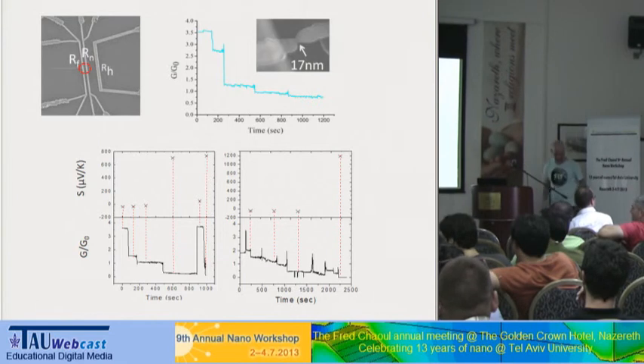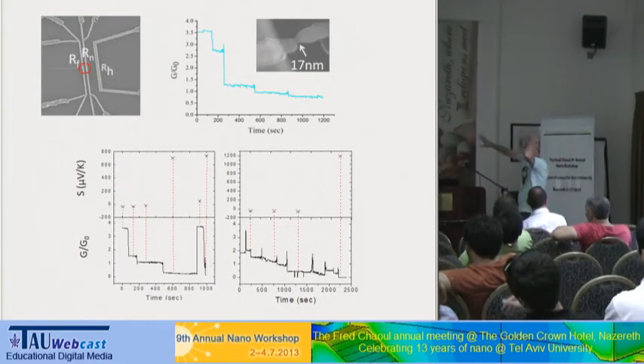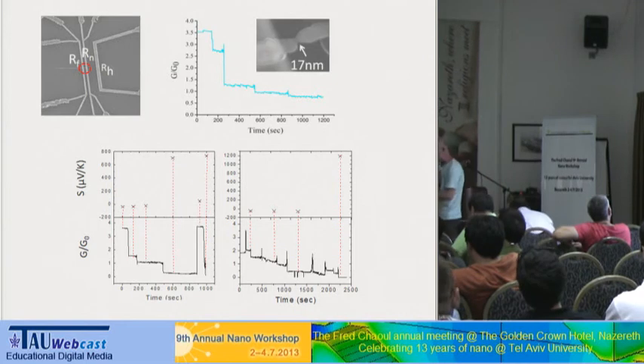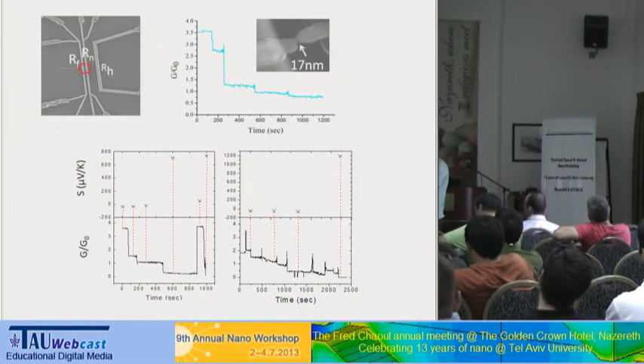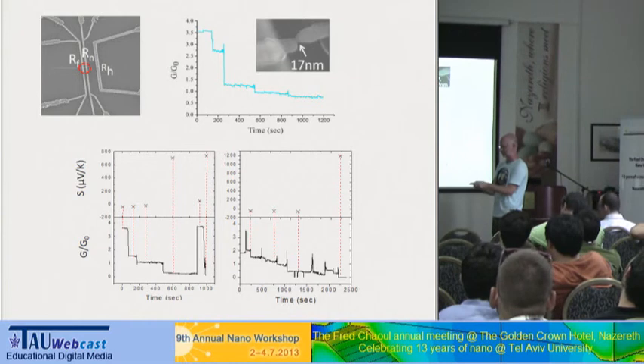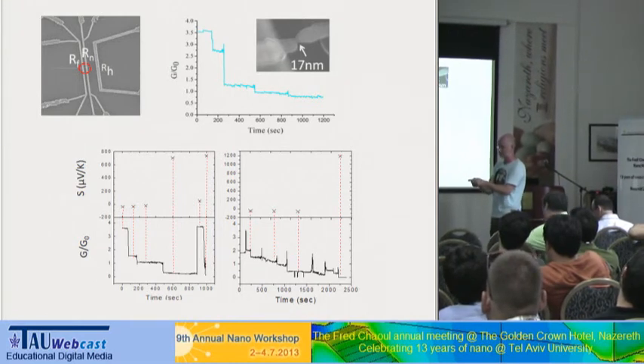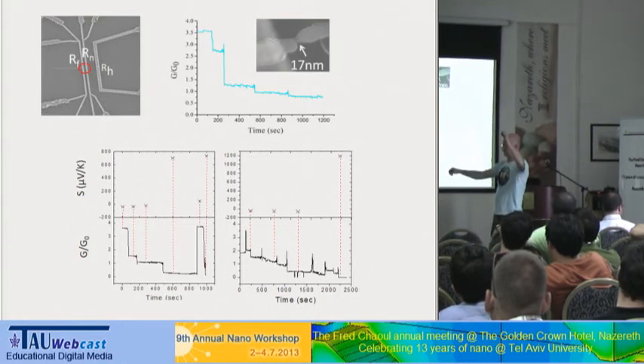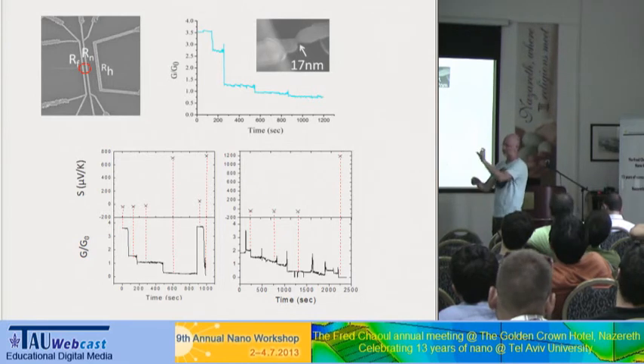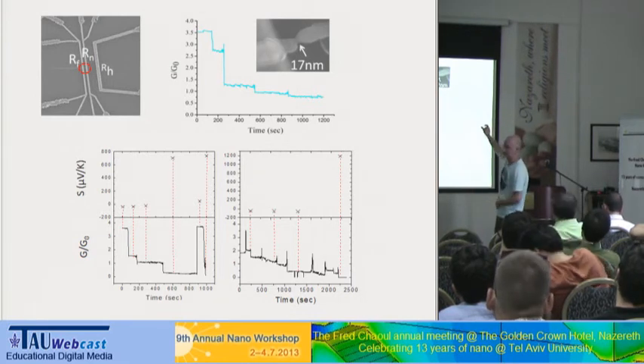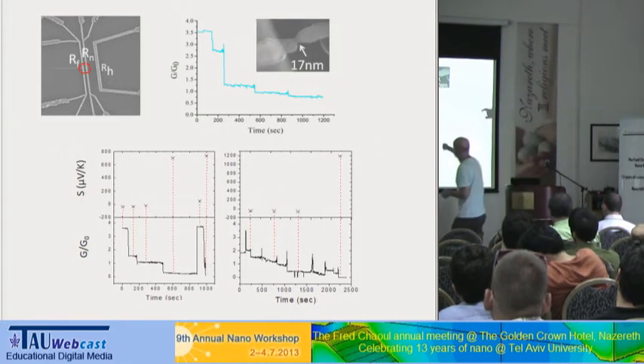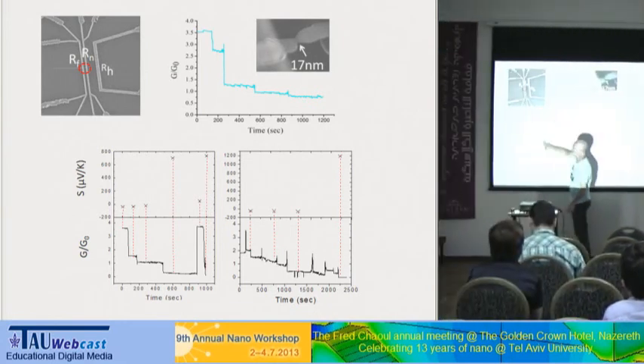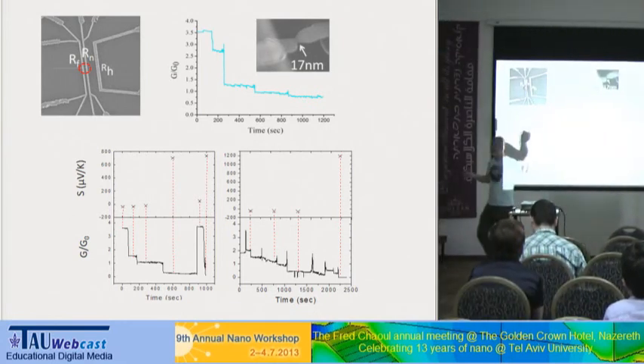That's a good question. So what we do is the following. I didn't go into the details here. So you have, let's say, 50 nanometers in length of a wire, and the constriction is much smaller than that. So you have a delta T over this structure. You can assume that this delta T is linear, so then you know what should be the delta T over your constriction and calculate the Seebeck based on what you're measuring, because the Seebeck of the constriction is much higher than everything else that is contributing. Because that's the dominant feature.